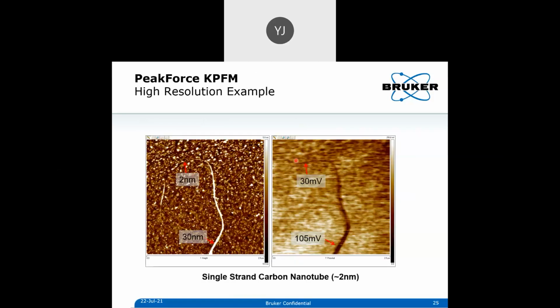And here is on the sensitivity part. So it's a single strand carbon nanotube, and it's only 2 nanometers at the very, very edge, right? And you can see here the KPFM data even able to clearly identify such a small material in a work function data. You can see in the topography, and you can clearly differentiate it from the substrate, right?